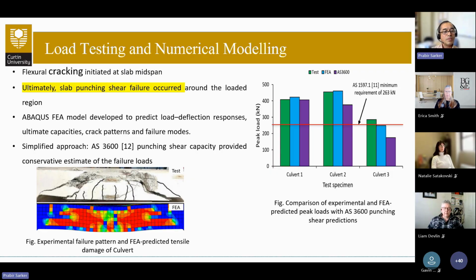It shows some simulation by finite element analysis using the Abaqus software. A model has been developed that can predict the load deflection response and ultimate capacities, with the crack pattern and failure modes, reasonably well.